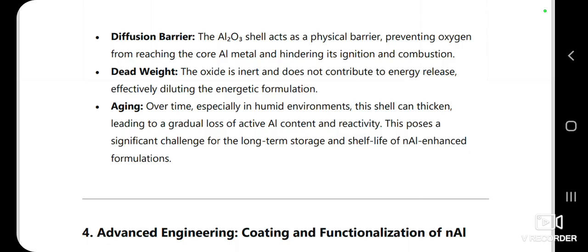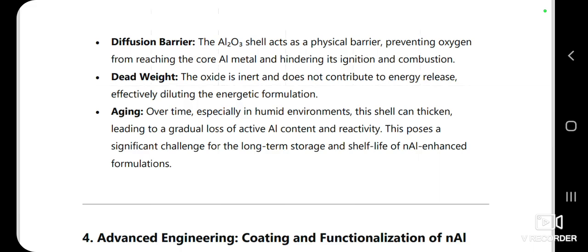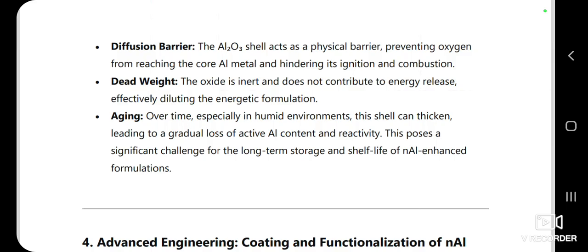And the next problem is the dead weight problem. This oxide doesn't contribute to energy release. It just dilutes our formula. And the next is the aging problem: over time, especially in humidity, this shell thickens, gradually losing active aluminium content, and its reactivity also decreases. This poses a significant challenge for the long-term storage and shelf life of nano aluminium enhanced formulations. This oxide shell is why 100 grams of nano aluminium doesn't give you 100 grams of energetic material, you might only get 70 to 85 grams of actual fuel, and the rest is packaging.